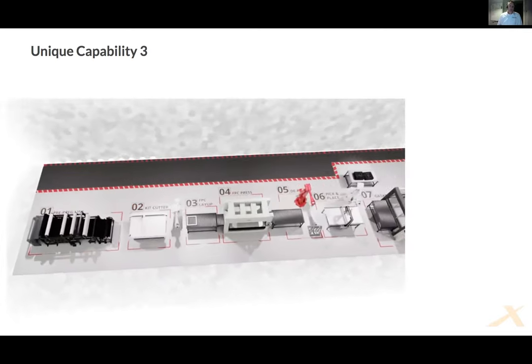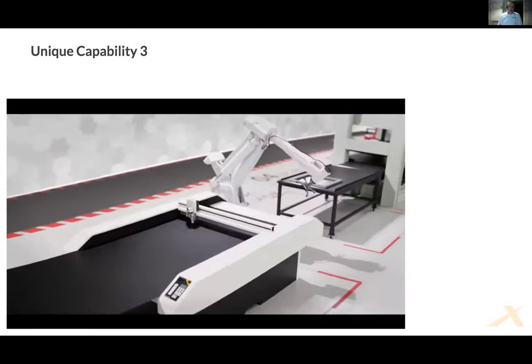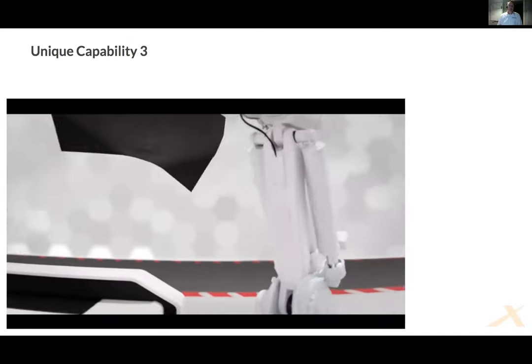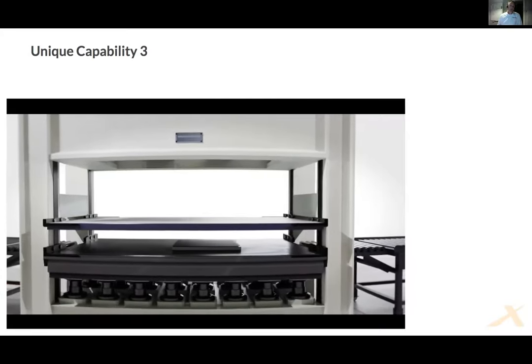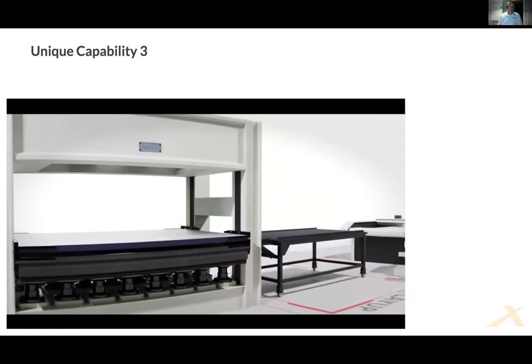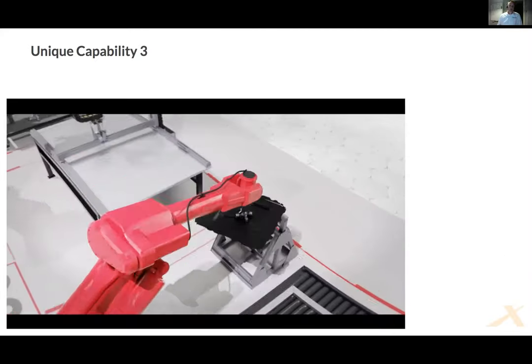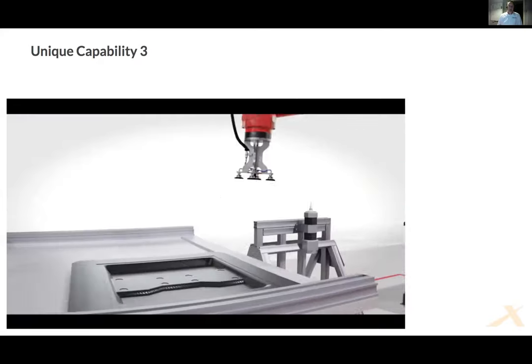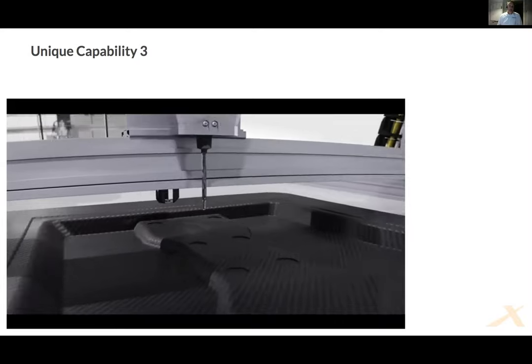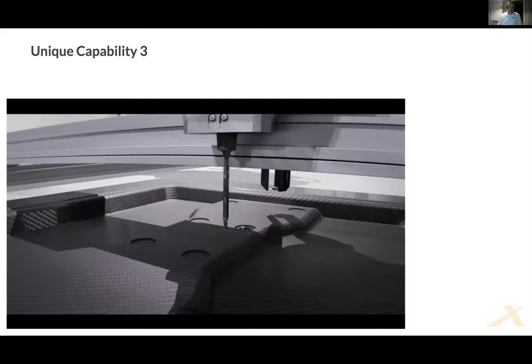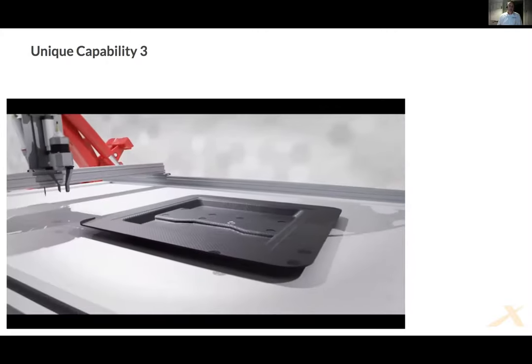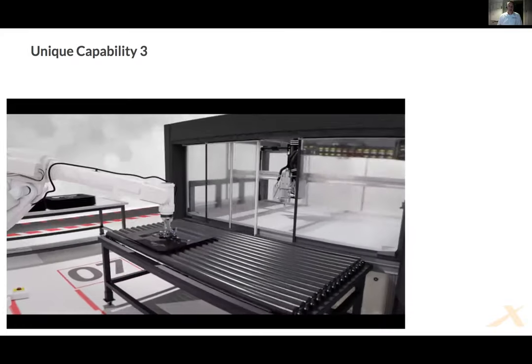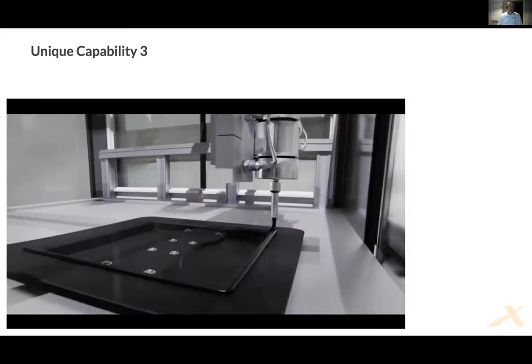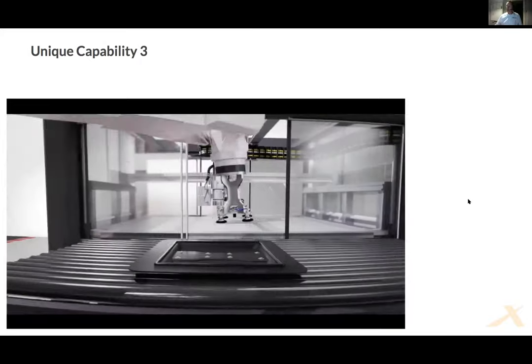As I mentioned, we're manufacturing the materials. The speed is the same speed that we have set on the run rate, which is the same as the flow of material through the kit cut, and then robotic pick and placement onto a tool. It then goes into a press. We can utilize the press with multi platens. In this animation, this is just a single daylight, but we do have multi daylights that we also use. This process goes through a cure system, and once cured, it is released. We can then perform, and we do now, the trimming and deburring of the component. Again, this is our own machine that we've designed and developed. This is pick and placement of metallic inserts, shown as an example. And then in this line, we have a liquid gasket for a customer that requires it. And then that's the end of that process.